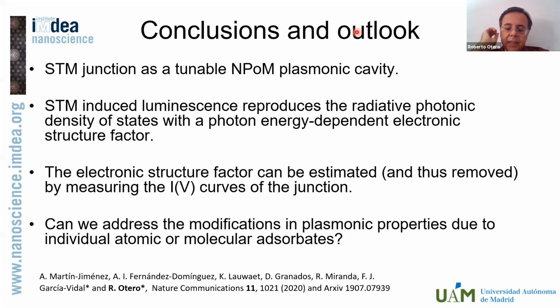There's an alternative scenario, and it is that you intercalate some other dielectric. For example, you place a few layers of salt on top of the silver layer, and then you place the molecule on top. That has been done, and it has the very interesting property that, depending on the molecule and whether everything works fine, in principle you're able to see excitonic emission. So you see much narrower peaks, even with a few bands at lower energy that are thought to correspond to Raman replicas of the main peak. So it's a lot of interesting work to be done.